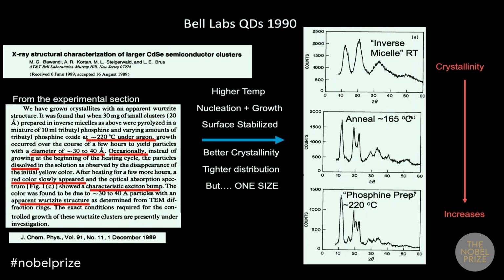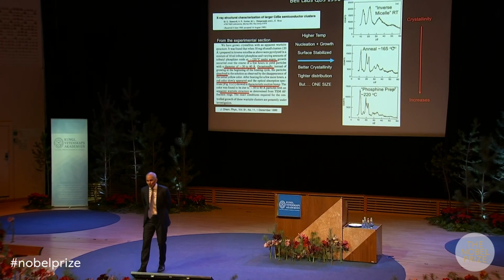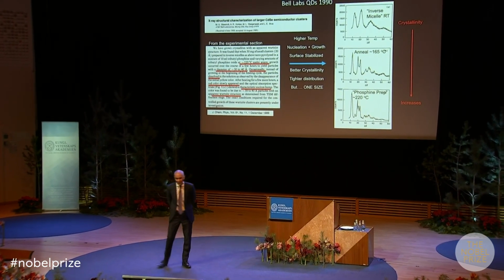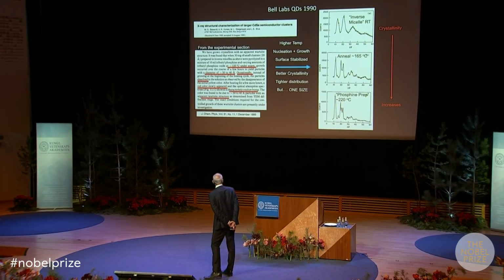We did X-ray analysis, and the width of the peaks that you see on top are an indication of the coherent size of the crystal that's in it. So broad peaks means that the material is mostly amorphous, and sharper peaks means that it's more crystalline. And so as you see that, as you anneal at higher temperature, the crystallinity also increased.